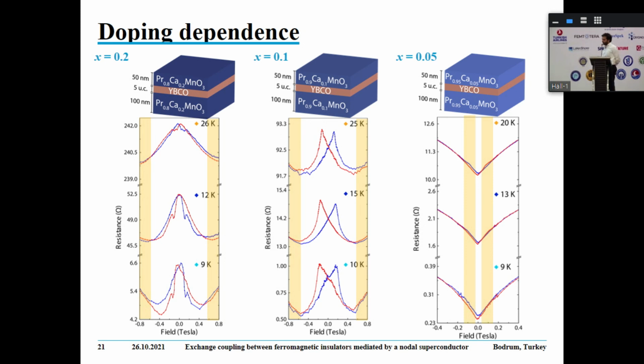The model of Mario just considered this nodal D-wave state and its order parameter, and basically it's consistent, if you want, the thickness dependence with this idea of these Fermi pockets that form on the Fermi surface of the YBCO. No, we did not consider this hybrid order parameter, to be honest. But we try to minimize the complication of the models. But that's a good point.